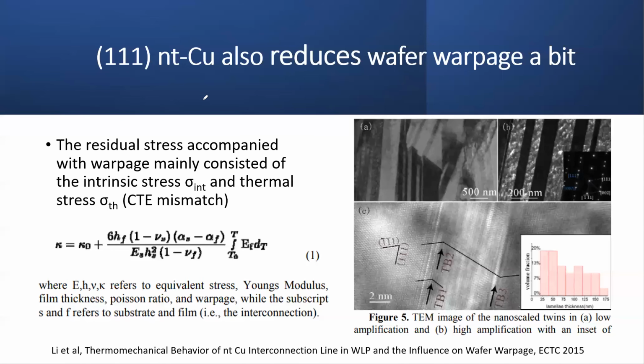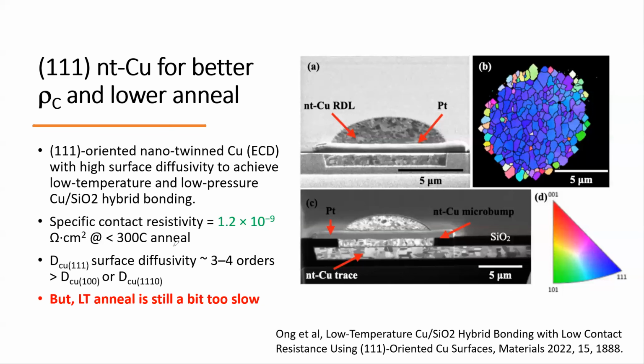Then there is nano twin copper, okay? They found out that if you could do it, it's pretty good. What I mean by pretty good is that it actually has a much higher surface diffusivity than the regular one. People found that 111 oriented nano twin has a lot of twinning, a lot of defects, done by electrochemical deposition. If they are fine grain, it helps you a lot, and it has a very high surface diffusivity. And very high surface diffusivity means that it's easy to deform.